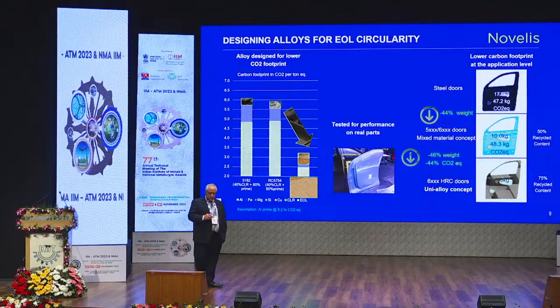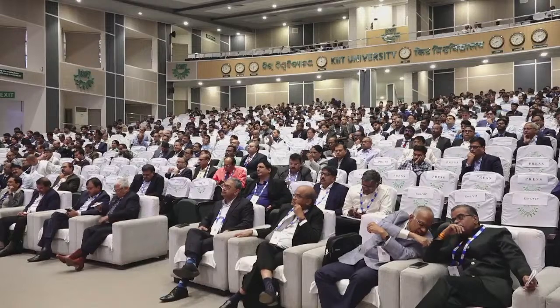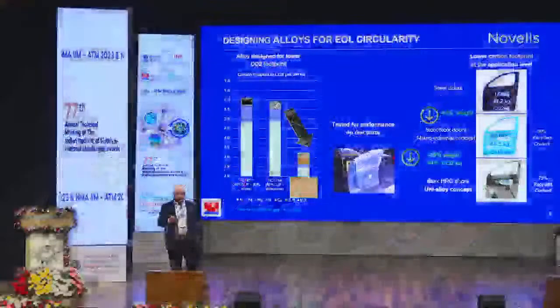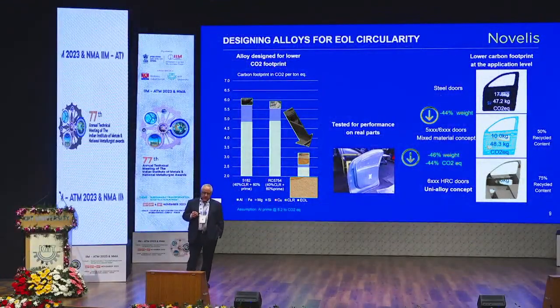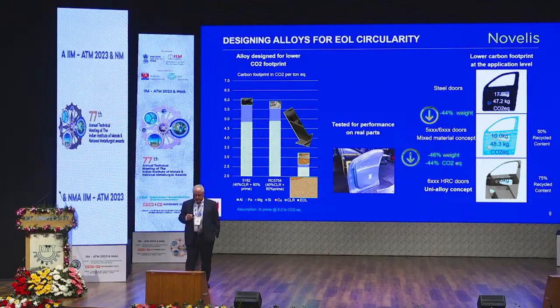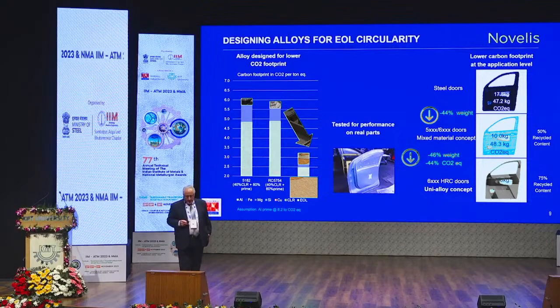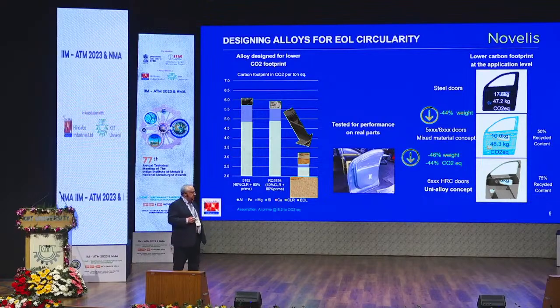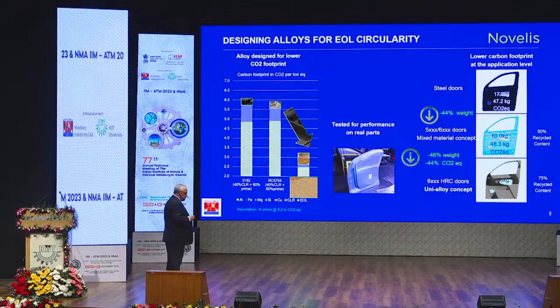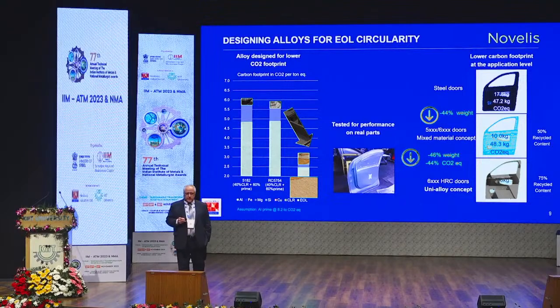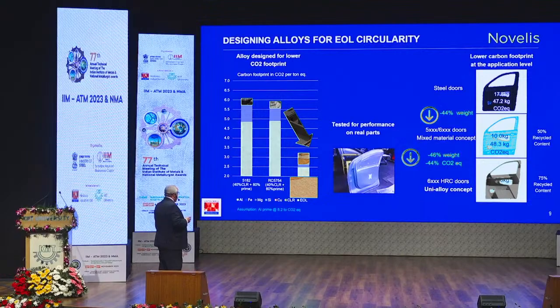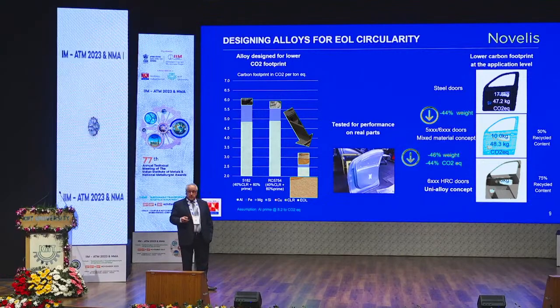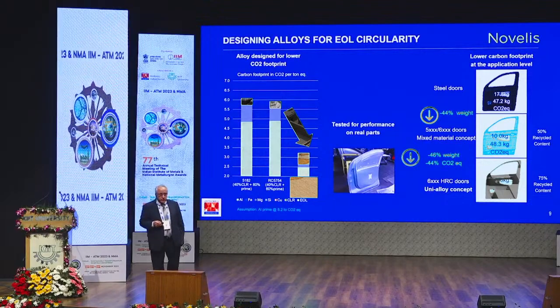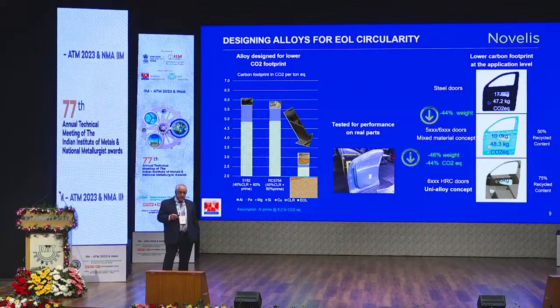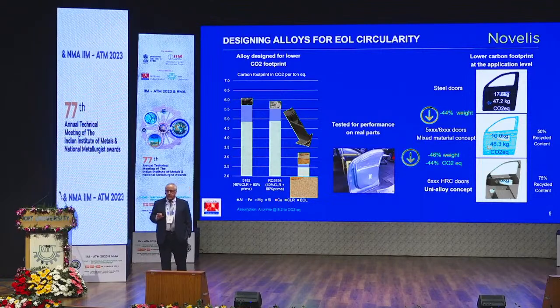Developing alloys is something important also. Usually the doors are made, or very often the doors are made, of inner 5,000 alloys and outer 6,000 alloys, because the 5,000 alloys behave very well in terms of forming ability. So it's very convenient for the inner parts. And the problem is that these 5,000 alloys have a pretty high CO2 footprint. With the current average standards today, this is 6 tons of CO2 per ton. And the reason for that is, first, magnesium brings a lot of CO2 itself due to the process used today, mainly in China. And also because these magnesium alloys are not very friendly when it comes to recycling.